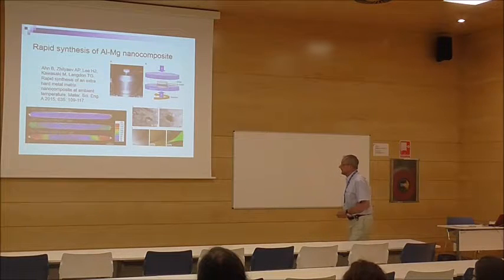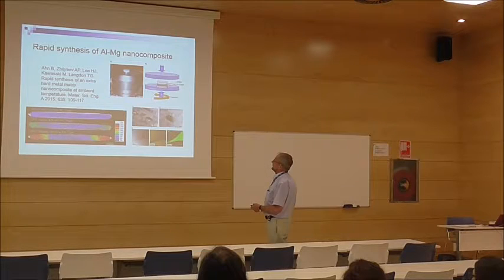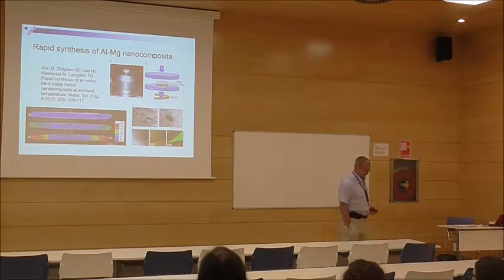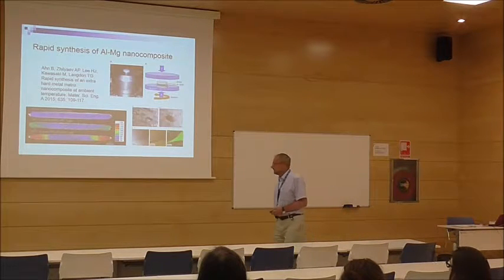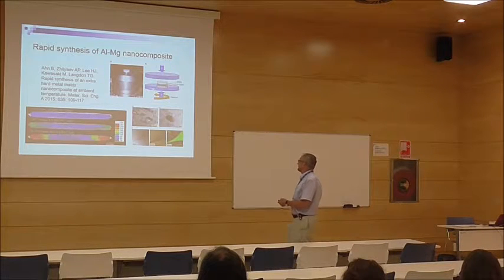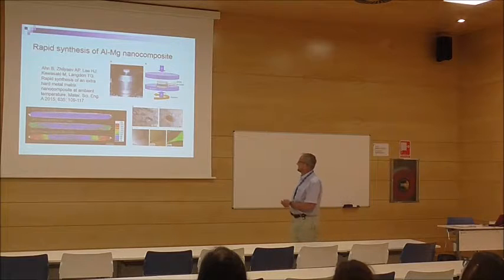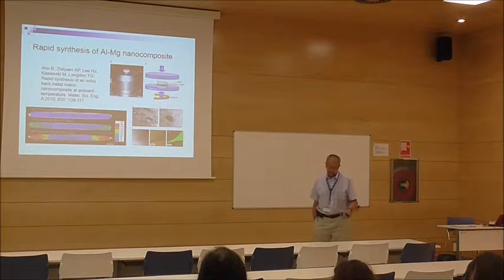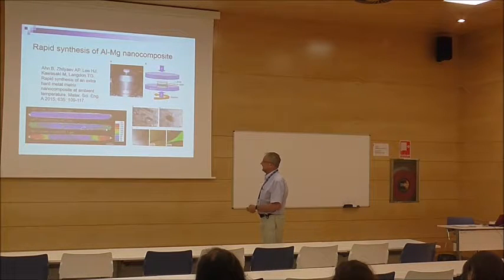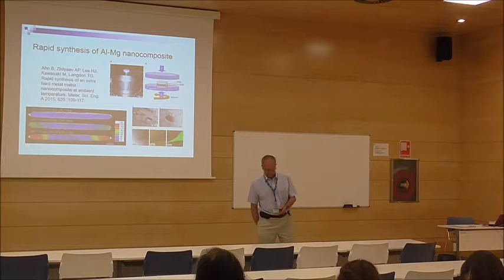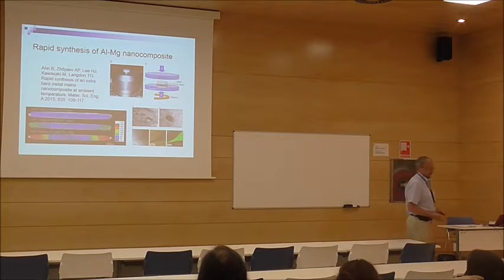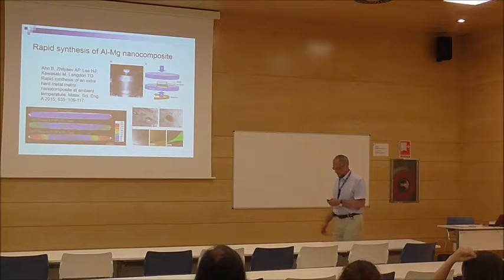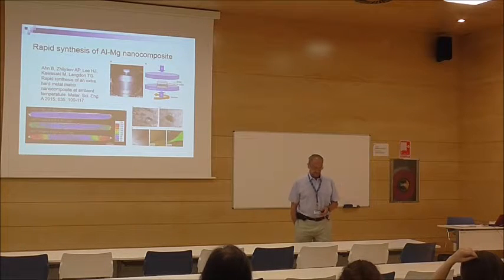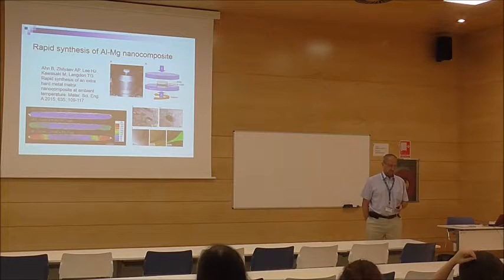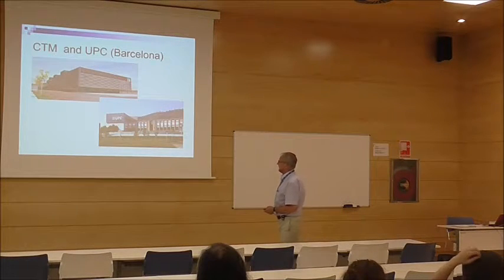So we did quite nice work with Megumi Kawasaki, who was a PhD student of Terry Langdon. Now she is a professor in Seoul, Korea. We put 3 samples, aluminium 1050 and ZK60 between them, compressed them and made 5 rotations, and we got some increase in hardness at the edge, and after 1 and after 5 turns we got intermetallics at the end. Actually, at room temperature, by placing 3 pure metals, we got intermetallics. I guess that doesn't happen very often; usually it happens during accumulative roll bonding at higher temperature, 450 or something like that.